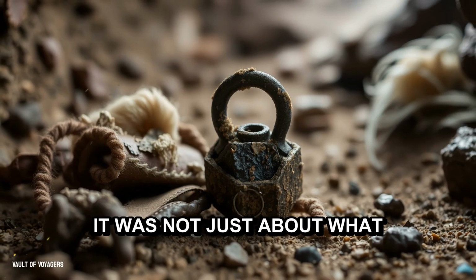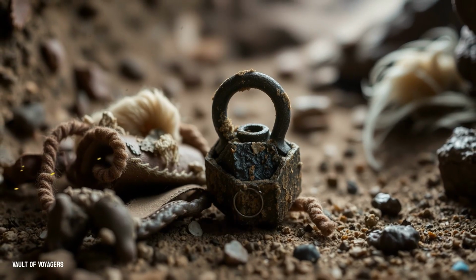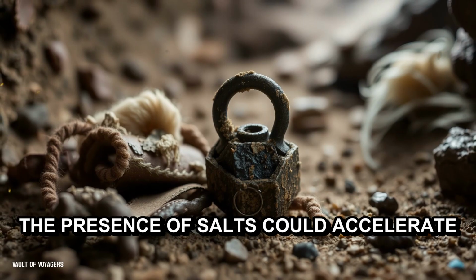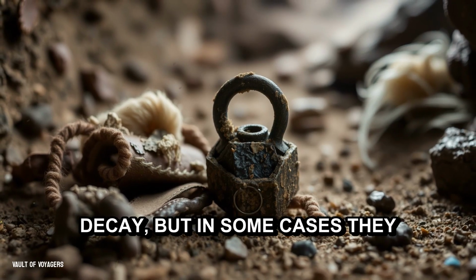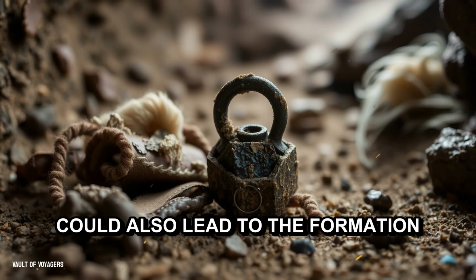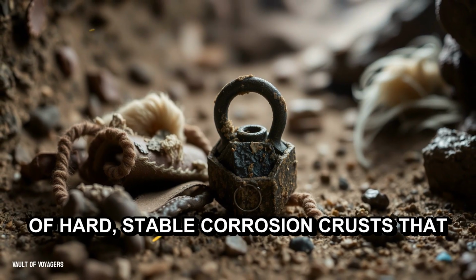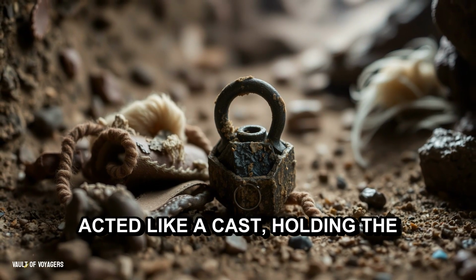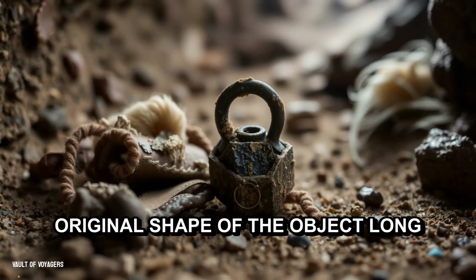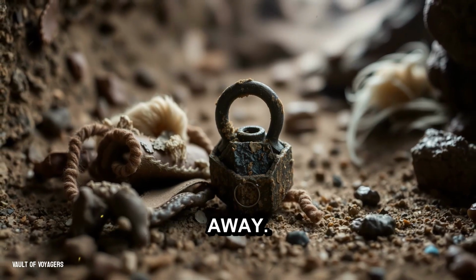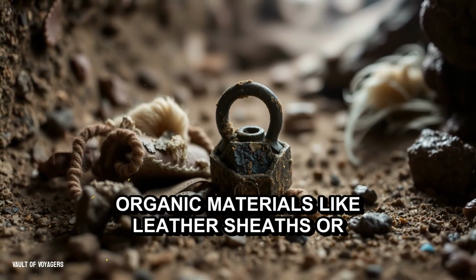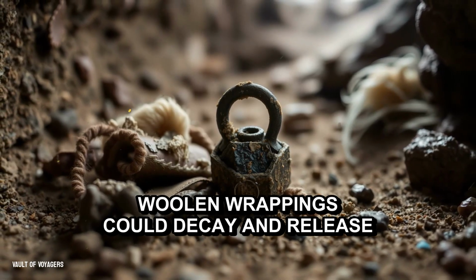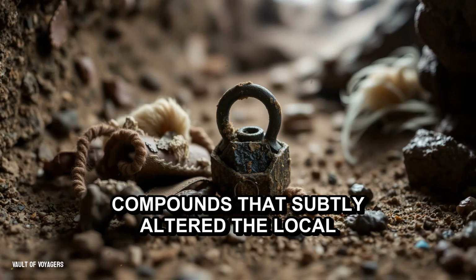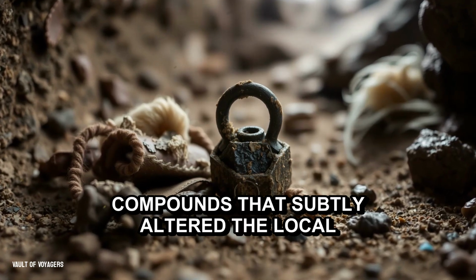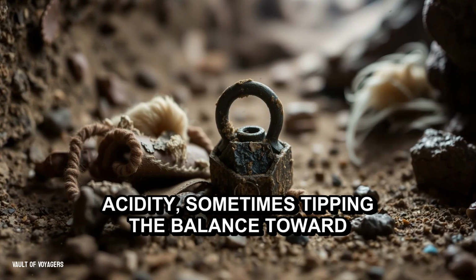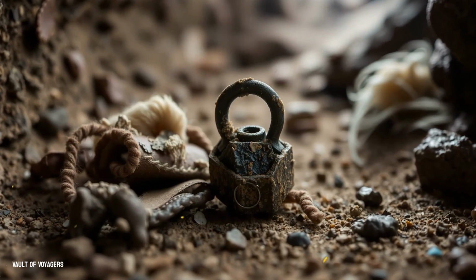It was not just about what was buried, but where it was buried. The presence of salts could accelerate decay, but in some cases, they could also lead to the formation of hard, stable corrosion crusts that acted like a cast, holding the original shape of the object long after the metal within had wasted away. Organic materials like leather sheaths or woolen wrappings could decay and release compounds that subtly altered the local acidity, sometimes tipping the balance toward preservation.